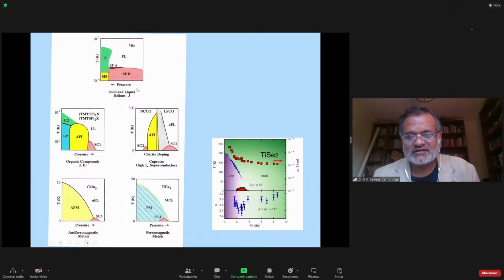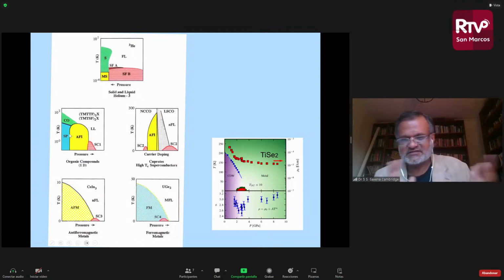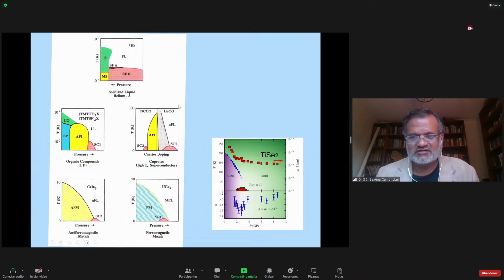So you have solid-liquid helium transitions you can see here. In organic materials, you see superconductivity and insulating states all being tuned into the critical points and states emerging there. Of course, you hear a lot of discussion regarding high-Tc or oxide superconductors, but also similar ones, like the pnictides. Where I started my work was in good metallic magnets, the heavy fermion variety, f-electron systems of cerium indium-3 and UGe2, so antiferromagnets and ferromagnets. But these things can also happen in CDW systems, where you see something similar: suppression of a state and superconductivity emerging in that corner.